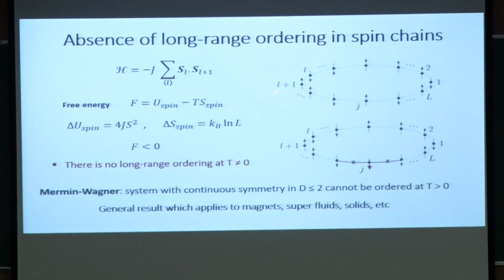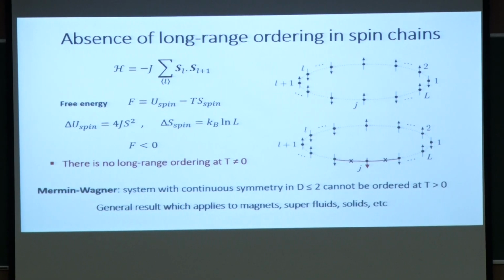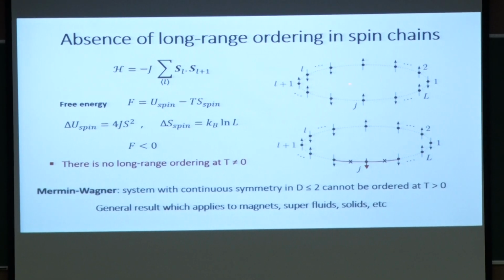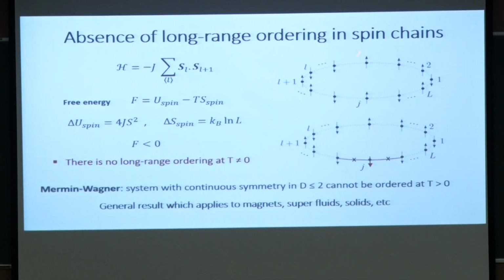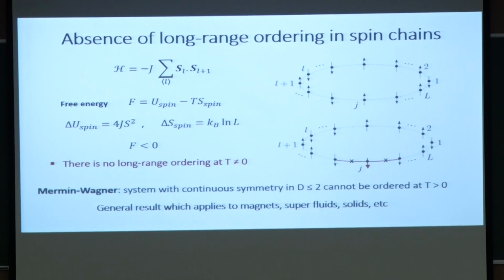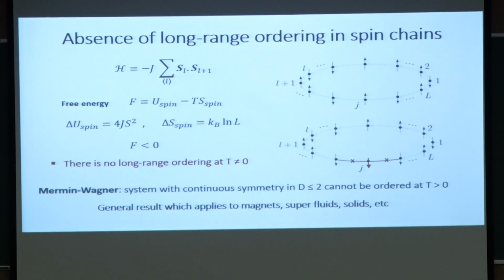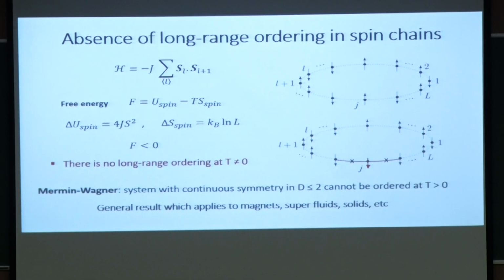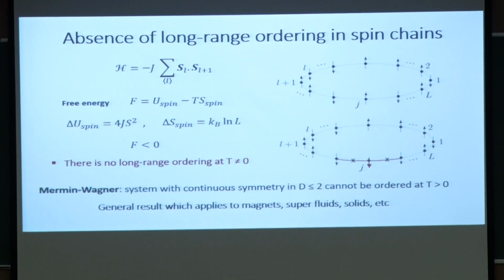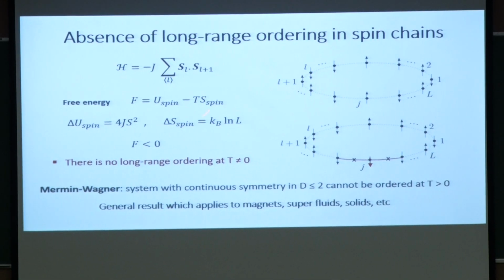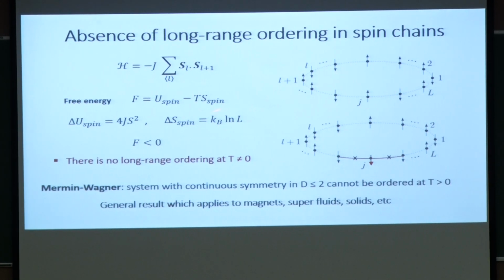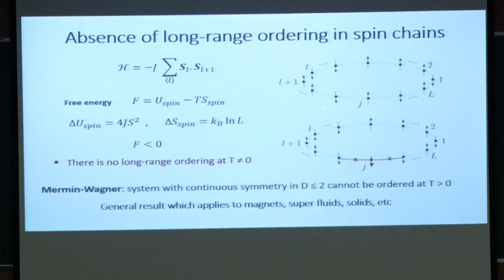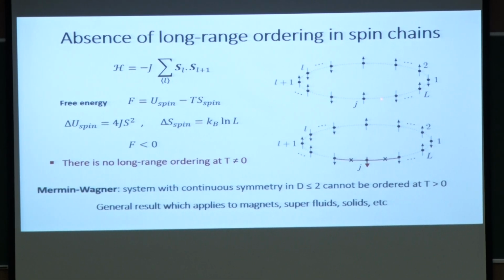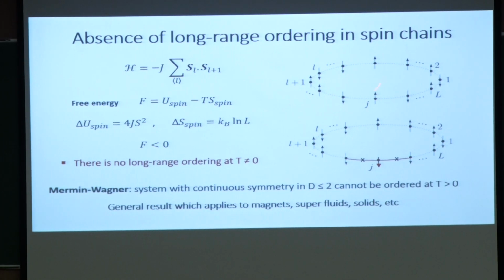So let's look at now the chains. In the spin chains, there is no long range ordering, which was mentioned in the previous talk also. In fact, Heisenberg spins in dimensions 2 or less do not order magnetically. All right. So in order to argue that, you can use this free energy argument. So here I have taken the spin to be a classical spin. It's just an arrow. It need not be a spin 1/2. I have left the spin size arbitrary.